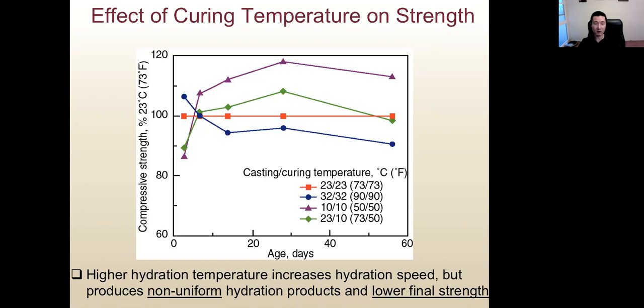However, the strength after around a week or so will be lower when we increase the curing temperature. The reason for that is when we increase the temperature, the hydration speed will increase, so we have a higher early age strength.